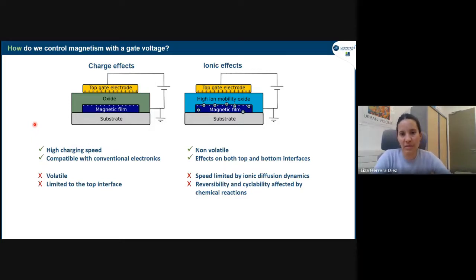Now, this is where ionic effects start becoming interesting. So the device design can be seen pretty much in a similar way. So then we have a top electrode, a bottom electrode, which is a magnetic film, and some oxide in between. But here we will particularly go for an oxide that has a high ion mobility. So of course here, if we apply a voltage, we will still get charges accumulated at the surface of the two electrodes. But what we want here is that this electric field that we create will be enough to actually move ions in the oxide, not just polarize it electrically. And these ions can go up to the magnetic film, and the effects can be very big.